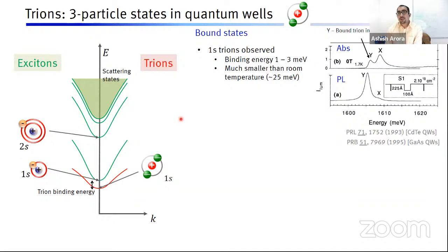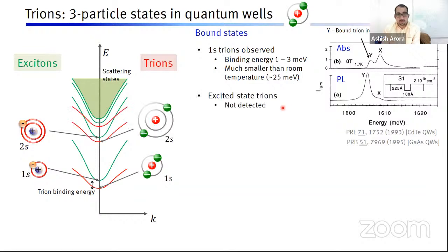So these trions were first observed in doped cadmium telluride single quantum wells, in absorption and in photoluminescence, around the 1990s. And the binding energy is very little. It's of the order of 1 to 3 meV. So these experiments are done at very low temperatures. For example, here it's 1.7 Kelvin temperature.